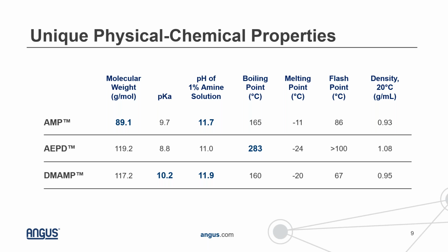pH of a formulation. If you look at AEPD, right, this has a different chemical composition. And what stands out in the case of AEPD is its high boiling point. So the boiling point of 283 is much higher than AMP. It's a bit of a weaker base. You'll see the pKa is around 8.8. And then if we compare that to the third material, DMAMP, this is the highest pKa material. So it's a very strong base and is used in a lot of applications where you really need a strong basicity from that material you're using.